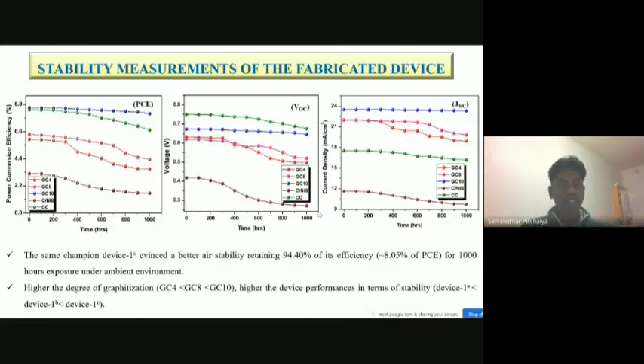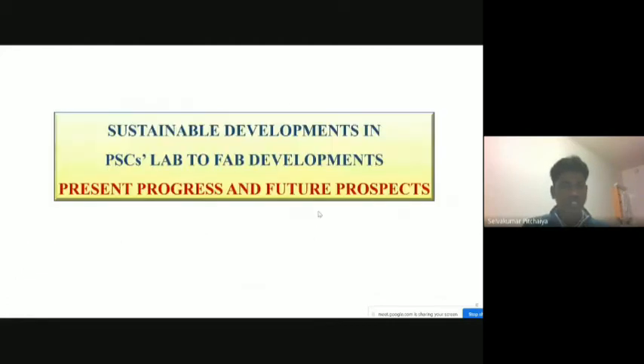This is the stability chart for our material, and the same champion device showed better air stability compared to all the other devices. It could retain nearly 95% of its initial efficiency up to 1000 hours. So we have achieved better long-term stability in our perovskite solar cell as well.